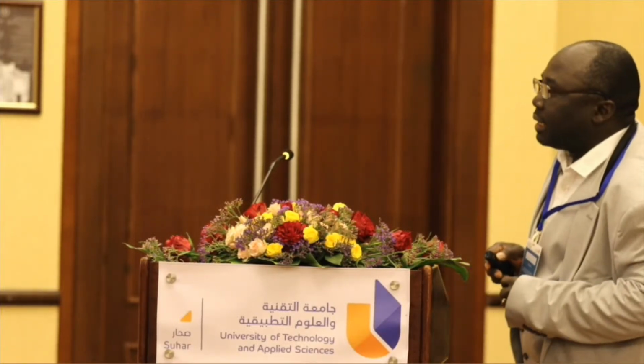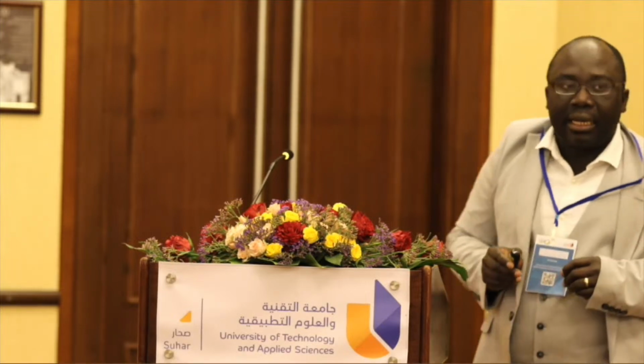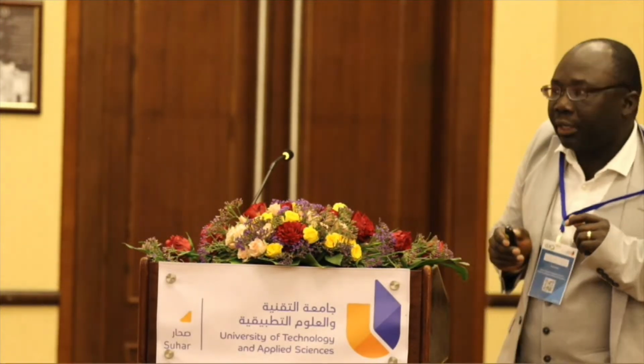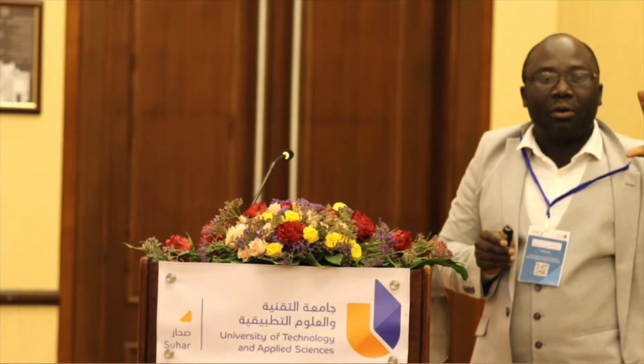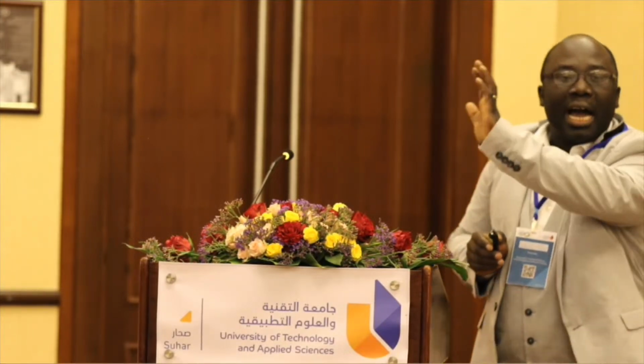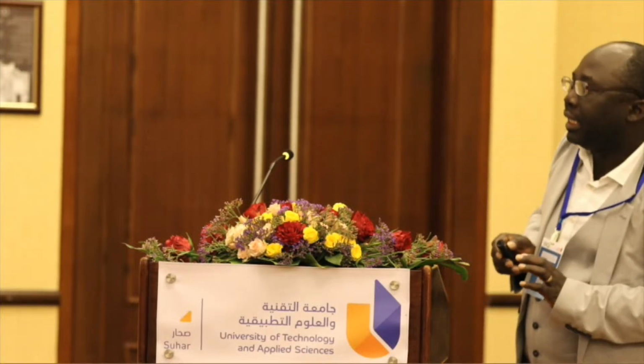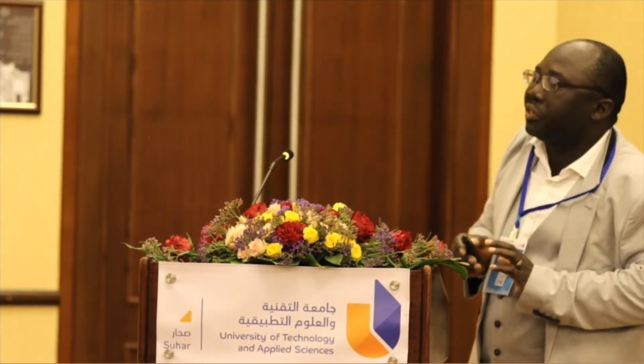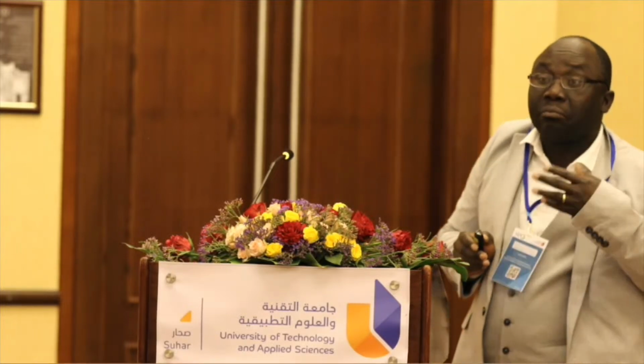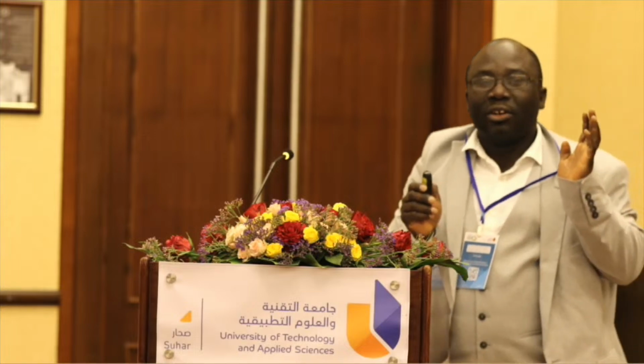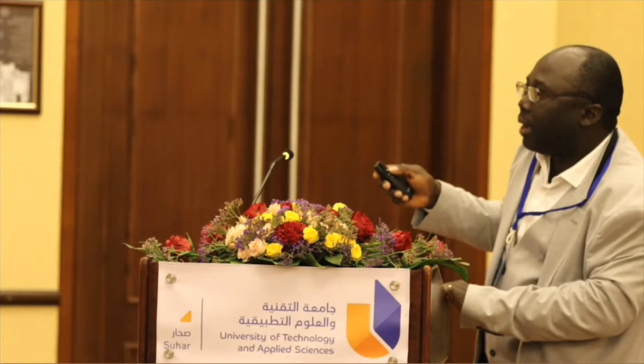The other problem is that ammonia cracking is an equilibrium reaction, okay? So you have ammonia breaking down on one hand and forming hydrogen and nitrogen on the other hand. Now, the problem is that this reaction is equilibrium limited. What that means is that as the ammonia is breaking down to form nitrogen and hydrogen, the nitrogen and hydrogen will tend to start recombining to form ammonia, all right? This presents a lot of challenge with the reactor development, and I will talk about that in a bit.